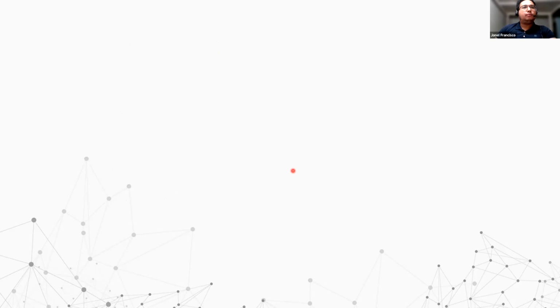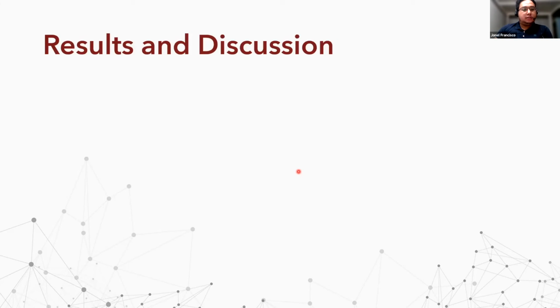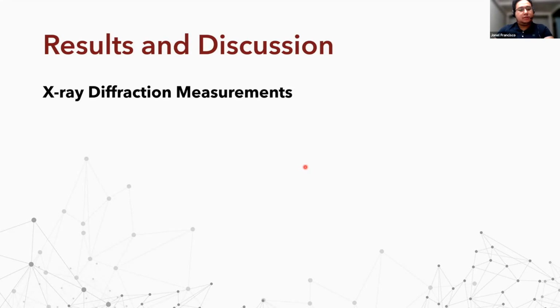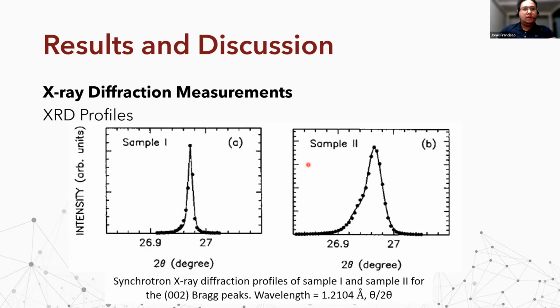Moving on to the first part of our results, we can see here the XRD profiles of sample 1 and sample 2. These are the synchrotron X-ray diffraction profiles for the 002 Bragg peaks. 002 corresponds to the out of plane measurement. The wavelength is 1.2104 angstrom and the scan method is theta 2 theta scan. As we can see here, sample 1 has a narrower peak than that of sample 2.